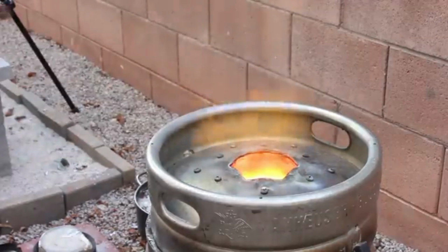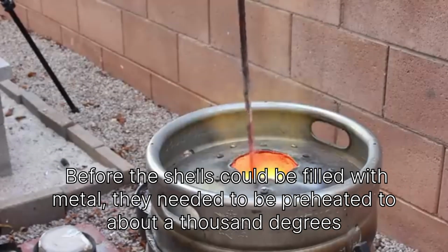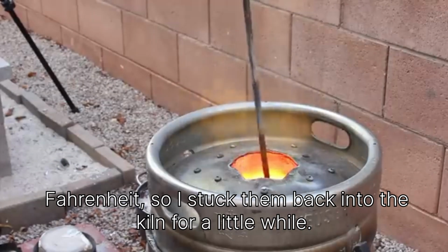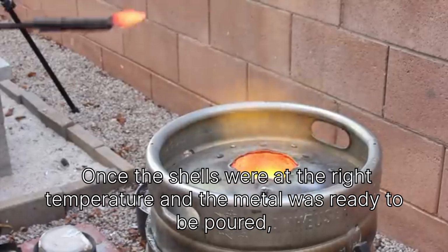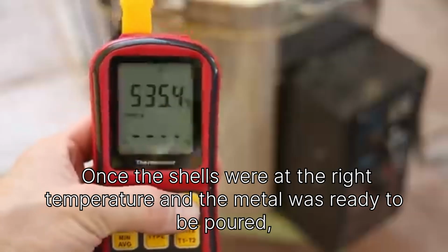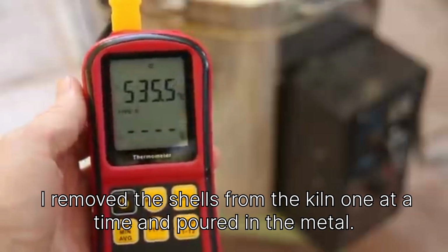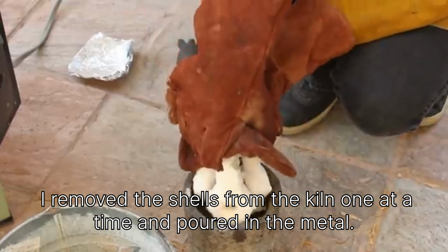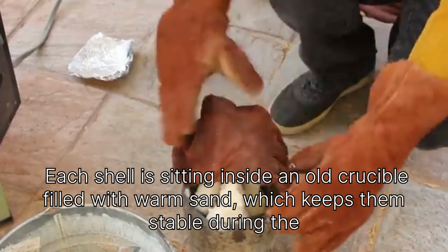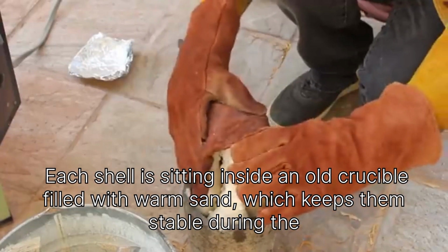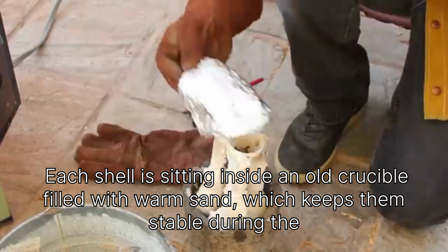Before the shells could be filled with metal, they needed to be preheated to about 1,000 degrees Fahrenheit, so I stuck them back into the kiln for a little while. Once the shells were at the right temperature and the metal was ready to be poured, I removed the shells from the kiln one at a time and poured in the metal. Each shell is sitting inside an old crucible filled with warm sand, which keeps them stable during the pour.